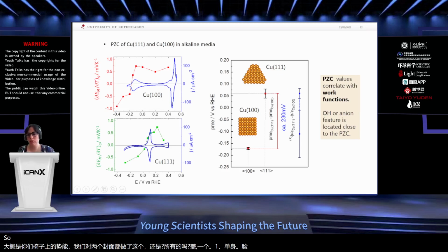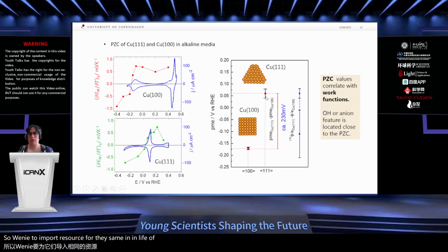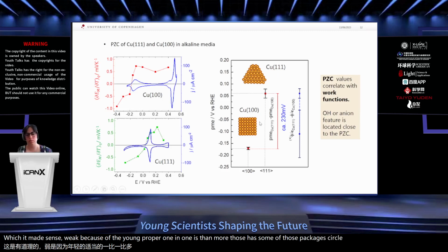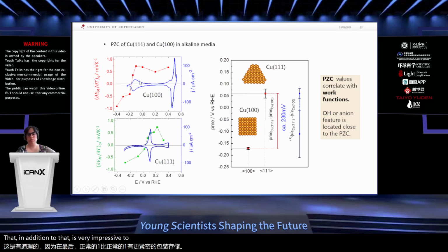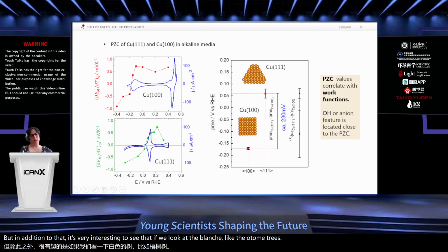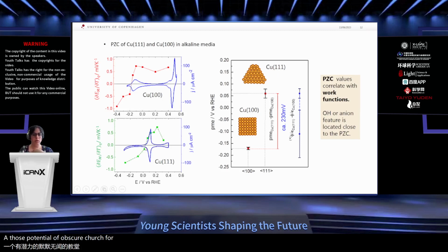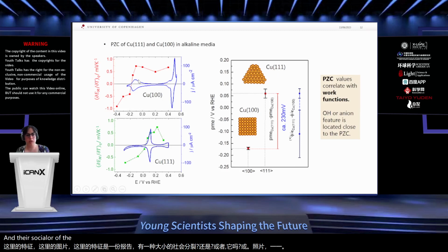What we found is two important results, at least in my opinion. First, the potential of zero charge of copper 111 is higher than that of copper 100, and the difference between these two potential of zero charge values is similar, or close, to the difference between work functions, which makes sense because copper 111 has a more close-packed structure compared to copper 100. But in addition to that, it's very interesting to see that if we look at the blank voltammetries, in both cases the potential of zero charge is close to this feature here and this feature here. This feature here is reported as the adsorption-desorption of hydroxide, or OH, on copper 111, and the adsorption-desorption of OH ions on copper 100.